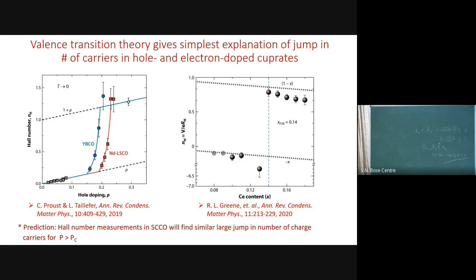There is no explanation of the plateaus. People don't even try those anymore. No explanation of why the Hall coefficient or number, if you go from 0.5 to 0.8, jumps exactly by a factor of 2. Look up Holmes's paper, 1987. So what I'm saying is the 65 Kelvin is one layer quarter filled, the 90 Kelvin is two layer quarter filled. If you say that there is copper, the coppers have got to be 1+. They don't want to be 1.2 here and 1.7.